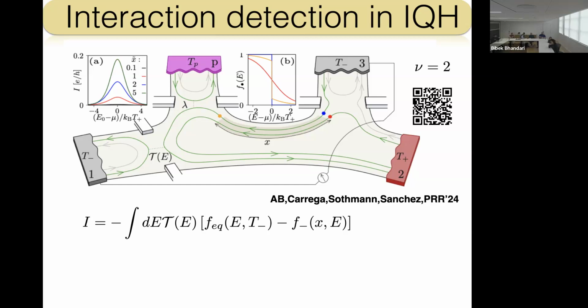Integer quantum Hall. And actually you see that if nothing happened here, the electron from the cold side arrives at the QPC. So in principle, a QPC is a device that can give you a thermoelectric effect. However, this has the same temperature, so no thermoelectric effect. However, this is hot, and this is an electron that goes nearby. If there is a heat exchange by interaction, you can bring energy over here, and this generates thermoelectricity. So in a certain sense, the local measurement of the thermoelectricity is a direct measurement of the heat exchange.